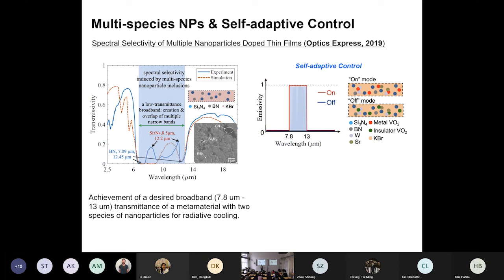Okay, this may not be good actually for outdoor application, for building applications. So we must find a material with a lower phase transition temperature. To lower that temperature, we consider adding these two nanoparticles. And people already demonstrated that, with tungsten and Sr, either or, this could lower the phase change temperature of VO2 from 68 down to room temperature, 25 degrees C, or even lower.